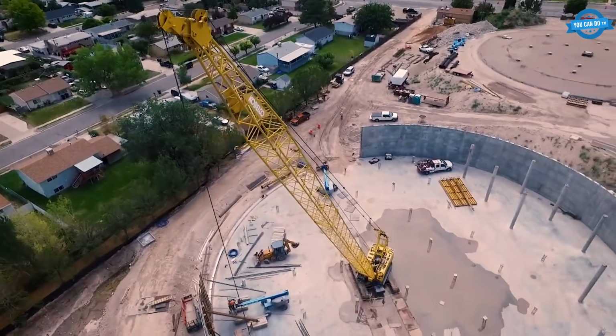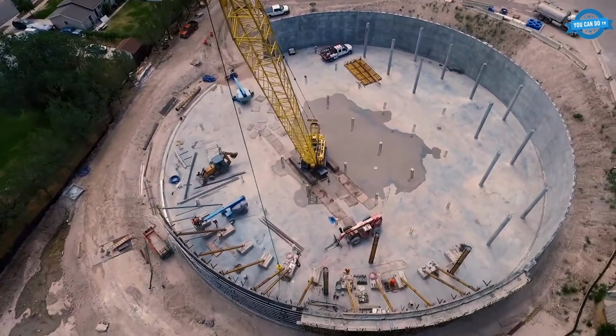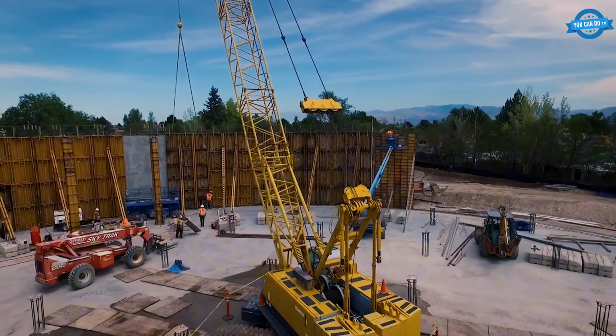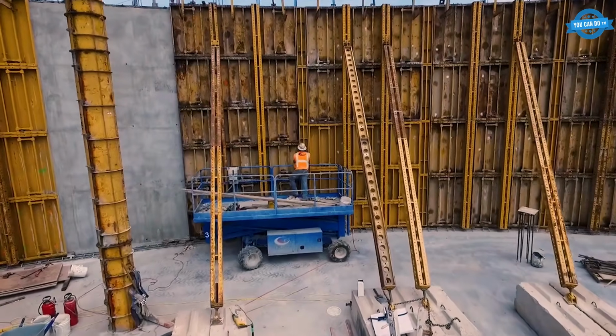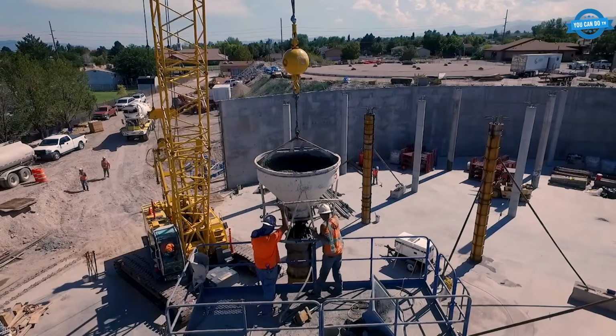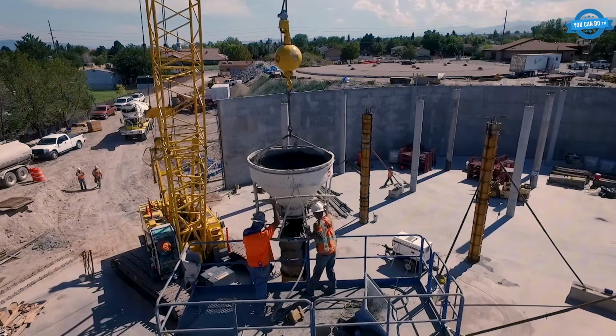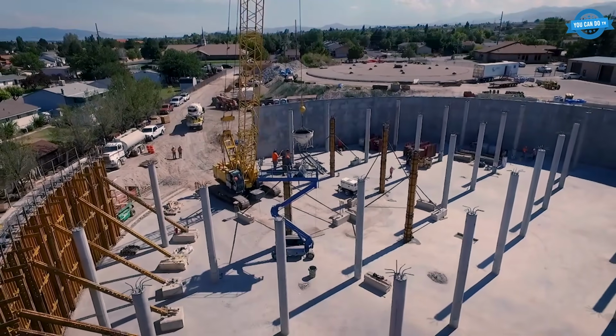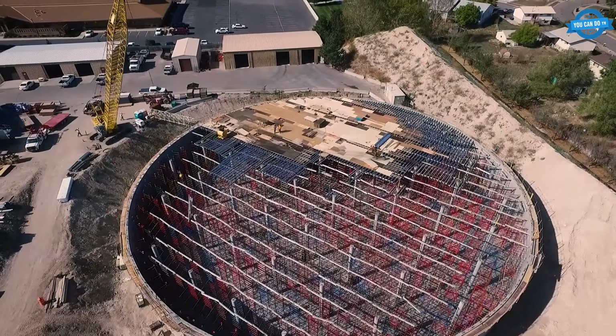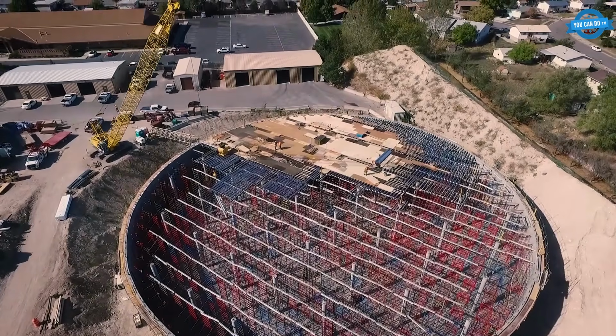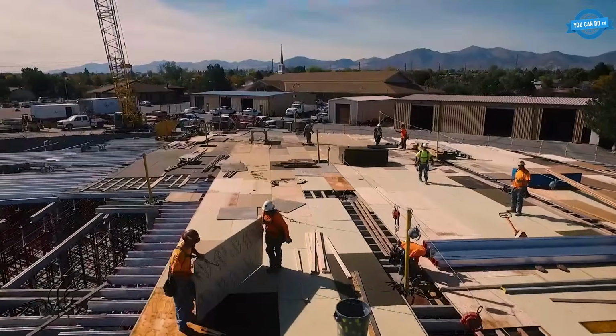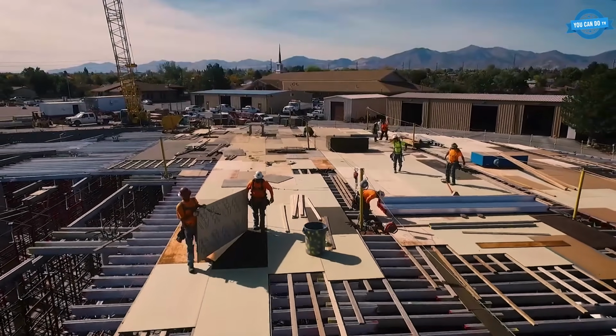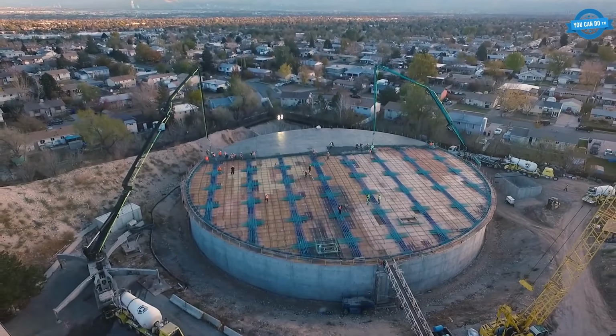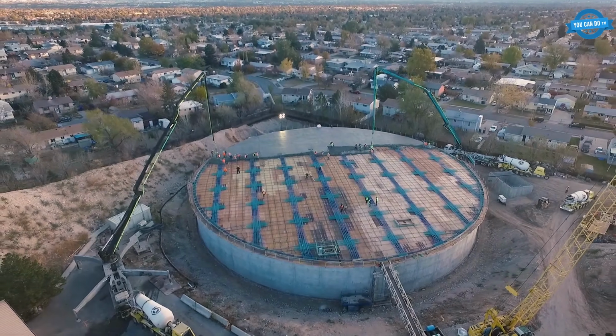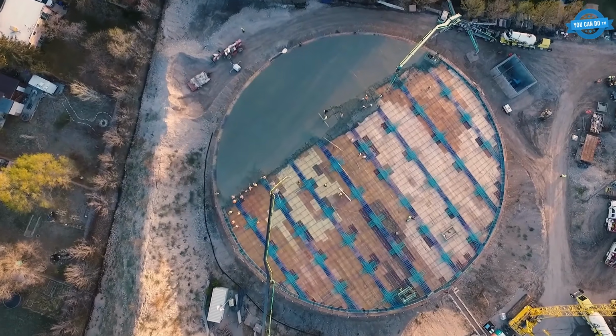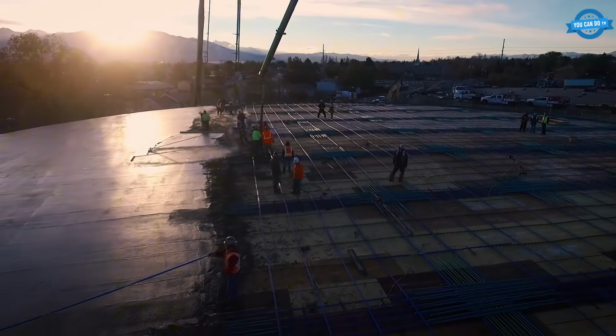That role belongs to large storage reservoirs and ground tanks placed along the network. The post-tensioned concrete tank built for Kearns Improvement District in Utah holds 5 million gallons of culinary water. A single ring of pre-stressed concrete with vertical and circumferential tendons tightened after the wall is cast. The wall is held in compression at all times so it cannot crack under hydrostatic load from the water inside.